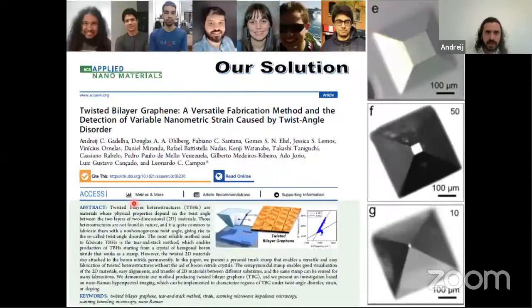hBN. And we developed a solution which was published here, and it is based on some pyramid stamps made from PDMS, which is kind of a silicone, and we can make them in a very controllable and reproducible fashion, large scale, and we can make pyramids with different sizes, like for example 100, 50, and 10.